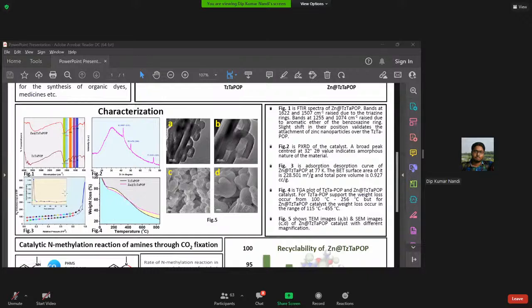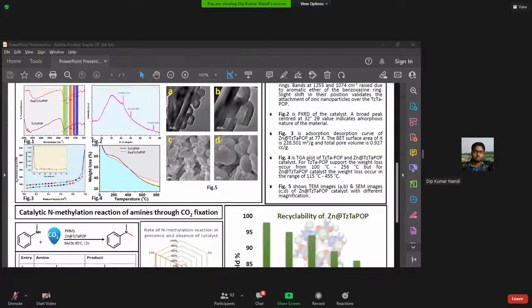And as we see the adsorption capacity, we can see this type of curve, which shows a high surface area, about 228 meters square per gram. The pore area is high, so it can absorb more chemicals inside, and the nature of its pores can be seen from the SEM and TEM data. You can see this here.